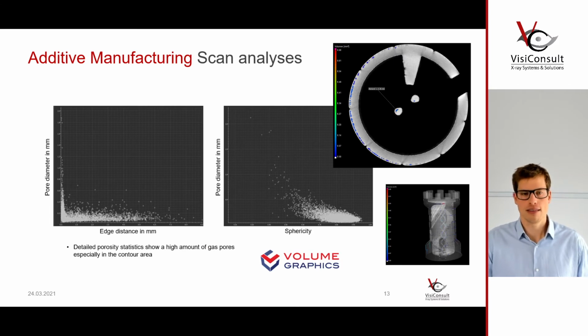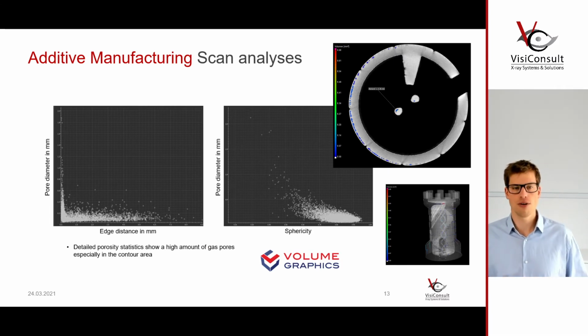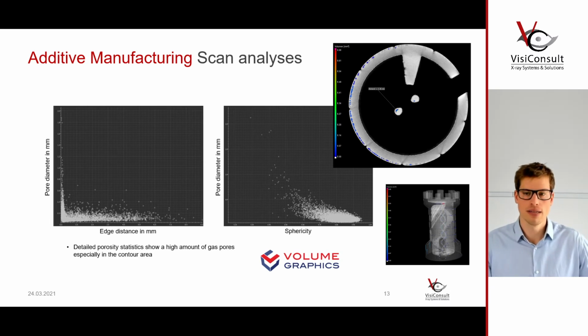And this here goes, it's a practical hint to all of you manufacturing engineers and designers out there: in additive manufacturing you have a non-uniform distribution of defects. Most of the time you have defects quite close to the surface, as you can see here in this area. And also this graph shows it quite well. Most of the porosities are in this area.